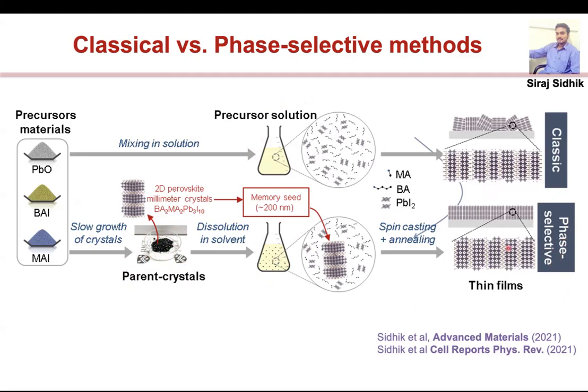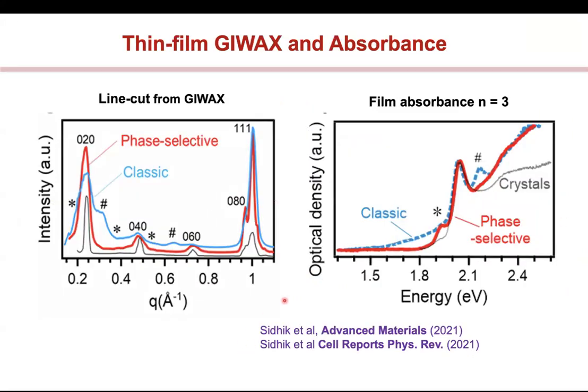And we call this method the phase selective method. And so it turned out that when we did this, we started getting films that had very high phase purity. What do I mean by that? Which means that when I make a 2D perovskite, for example, if I look at the plot here, what I get in the absorption spectra: if I'm trying to take a crystal which is n equals 3, which is only 3 octahedral layers, then I'll get absorption coming from exactly that N3 2D perovskite, not from other phases.